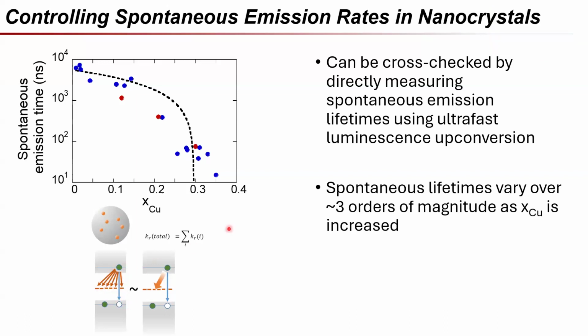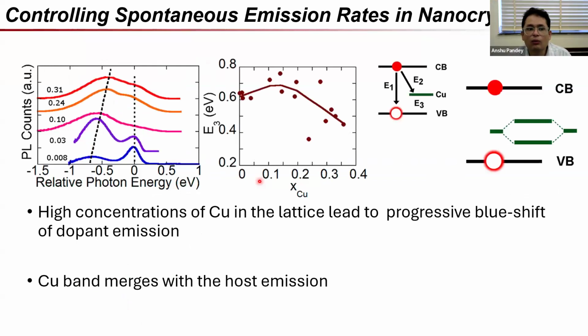And why is there a blue shift? Why is there the blue shift? Okay, again. If you see it, your band gap seems to be decreasing, right? You told the band edge is shifting. Right. So again, it's blue shifting because if you notice this particular graph here, or this schematic here. So firstly, this is the graph of blue shift. It's blue shift relative to the main host emission band. And the reason why this is happening is the copper energies are not changing. They are simply splitting, but all the oscillator strength is carried by the lower state. The outcome of that is, if you notice, initially I had to go this much energy, this was my emission energy, but now it will be this much. So this is higher energy, right? So this is why there is a systematic blue shift. This is approaching the host valence band.